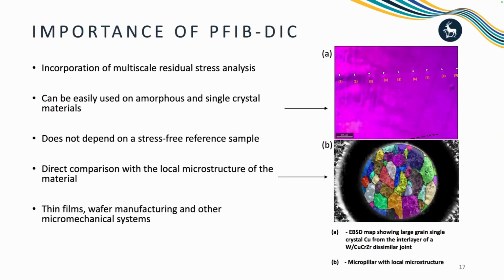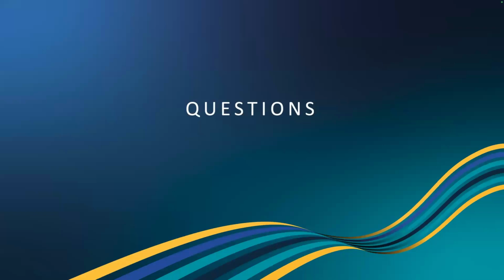So here is the importance of this method. In this case, we have two key points of importance for this technique. Firstly, we can measure the residual stress at high resolution. In this case it's 200 microns, but we can still make the resolution much higher. So for materials with complex interfaces, we can really measure the details of the residual stress distribution. And another thing, we can correlate with the microstructures to find out the localized Young's modulus and Poisson ratio, and find out the real residual stress distribution in the localized space. Here, that's it.